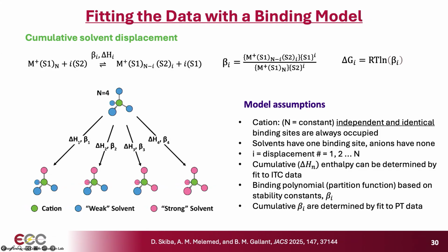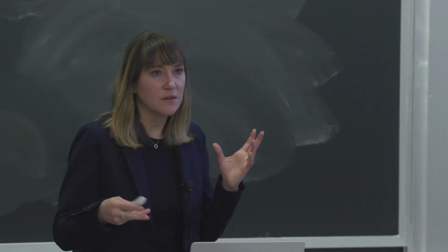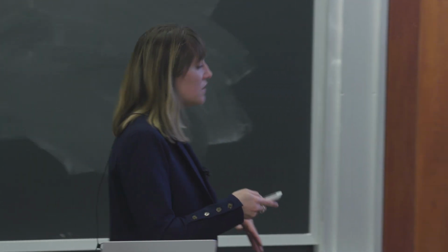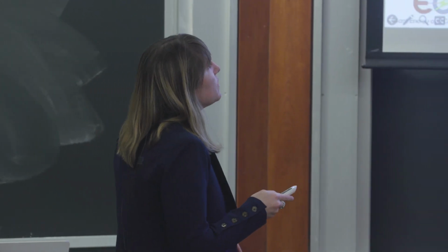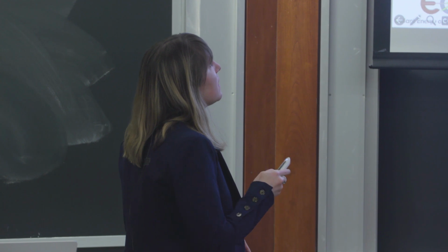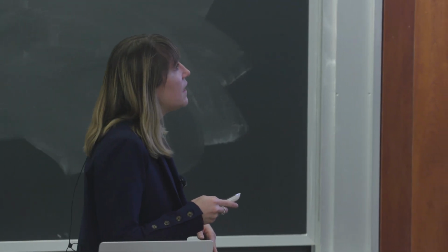So we model these interactions as sequential displacement reactions, okay, starting from solvent 1, going through sequential displacements up to a full coordination sphere of solvent 2. We can describe the reaction like this. We have corresponding stability constants shown here. And ultimately, this allows us to get to a binding polynomial that is effectively, conceptually, and mathematically equivalent to our partition function. The assumptions that we have to make are that the cation has a constant number of interaction sites and that the sites are independent and identical.